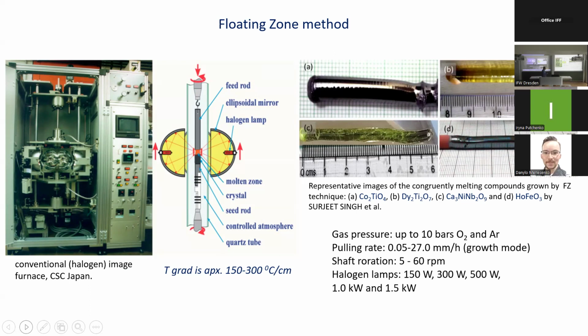You collect, by mirrors, all emitted light and focus it in one focal point common for all mirrors. If you place the tip of your feed rod in the focal point, you melt it, form a molten drop, touch it with the seed, and maintain a stable molten zone. Then you pass slowly through your feed rod upward, and so you get crystallization of your material. In this way, we could relatively easily grow many congruently melting compounds. Some of them are shown in these photos.